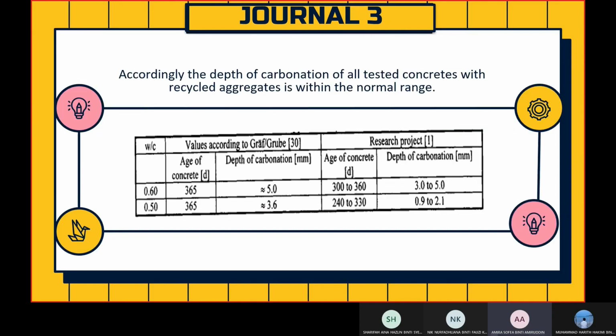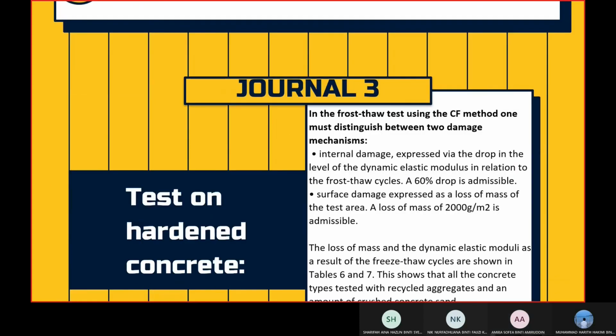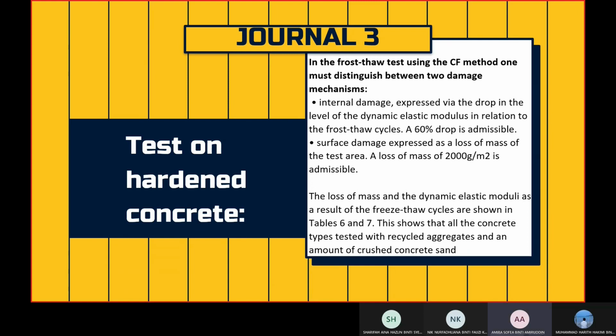The depth of carbonation of all tested concretes with recycled aggregates is within the normal range. Lastly, in the frost thaw test, using the CF method, one must distinguish between 2 damage mechanisms. First is the internal damage expressed via the drop in the level of the dynamic elastic modulus in relation to the frost thaw cycles. A 60% drop is admissible. Next is the surface damage expressed as a loss of mass of the test area. The loss of mass and the dynamic elastic moduli as a result of the freeze thaw cycles are shown in Table 6 and 7. This shows that all the concrete types tested with recycled aggregates and an amount of crushed concrete sand.